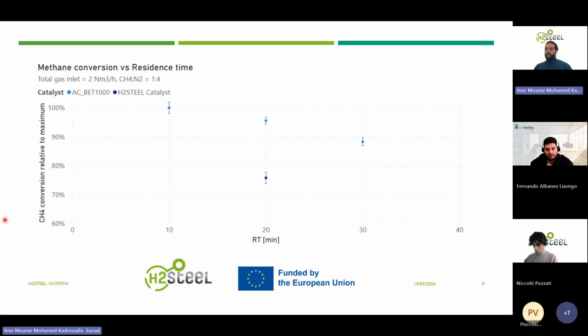The dark blue point, the one over here, represents the catalyst that was produced within H2STEEL, which is also tested at 20 minutes estimated residence time. These results, although they show a higher relative conversion of commercial carbon with respect to the in-house H2STEEL one, show a relatively close value to the commercial one, keeping in mind that one of the